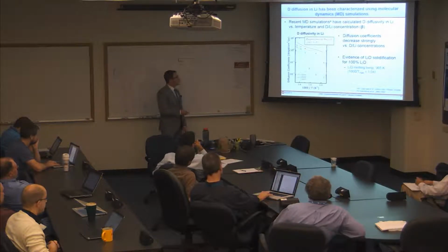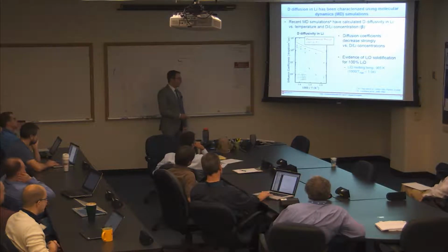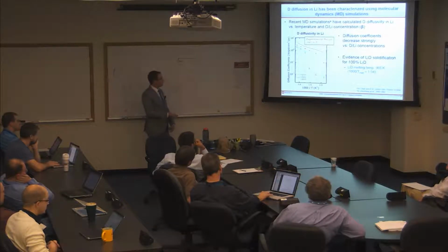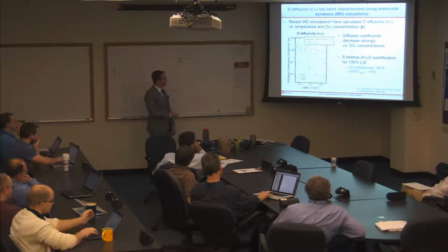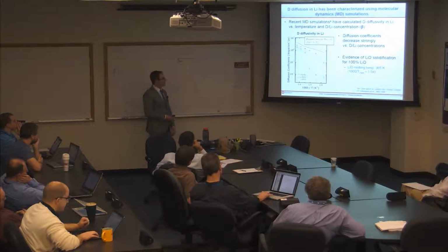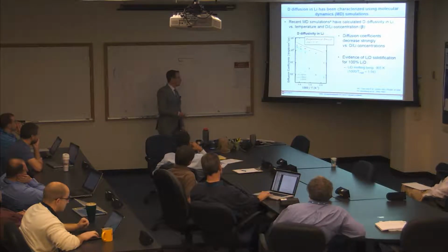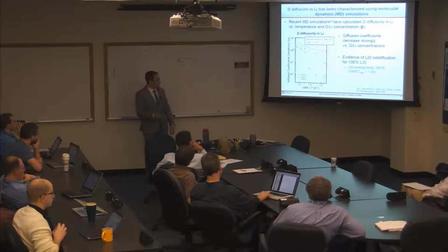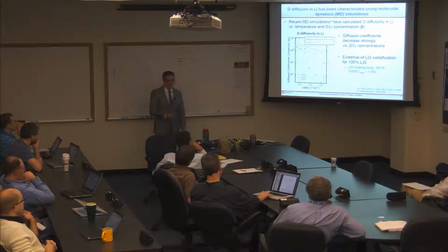So these simulations were molecular dynamics simulations performed by a group on campus led by Mohan Chen and his advisor, Emily Carter. And they calculated the diffusivity of the deuterium in lithium versus temperature and the concentration, which I call beta. And as you can see, they're given over here on the left. And the decrease here is due to the increasing concentration of deuterium in the lithium. And this bottom teal line here corresponds to complete, what I call saturation, which is a 1-to-1 lithium-deuterium ratio on the surface. So the diffusion coefficients clearly decrease very strongly versus concentration, as well as increasing versus temperature.